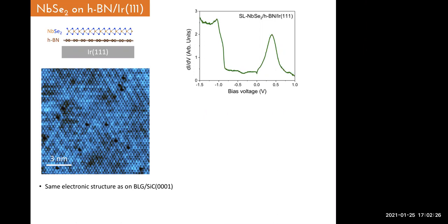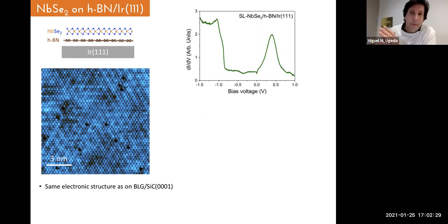Okay, so we have done this in order to rule out the existence of these peaks, in order to rule out the role of the substrate in the presence of these peaks. We have studied single layers of NbSe2 on a different substrate, not bilayer graphene on silicon carbide, but monolayers of hBN on iridium. So in principle, the electronic gap of hBN is 6 electron volts. So electronically, the 2D superconductor is in principle fully decoupled from the iridium. So this is the most isolated, ideal way we can work here.